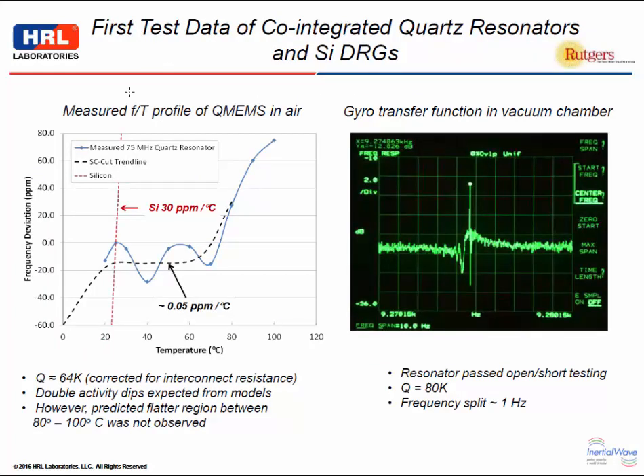So our first data showed very good performance on the silicon device and a reasonably good match with our models on the quartz device as well. So this is the measured FT profile of the quartz MEMS device measured in air. The Q after I corrected for this increase in interconnect resistance of 50 or 70 ohms in air was about 64K. We would expect it to be over 100K in the vacuum. And it did show the two activity dips that the model predicted. It didn't quite have the flatter region between about 80 and 100 degrees C that we were expecting. I'm not sure why that is, but we clearly need to do a little bit better design on the quartz.